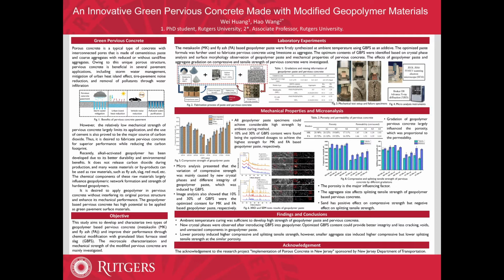If we further compare the specimens with F3 and F4, we can find that their compressive strengths increase from F3 to F4 for both metakaolin and fly ash-based pervious concrete. However, their splitting tensile strengths reduced from F3 to F4. So we believe the sand has a positive effect on compressive strength, but a negative effect on splitting tensile strength.